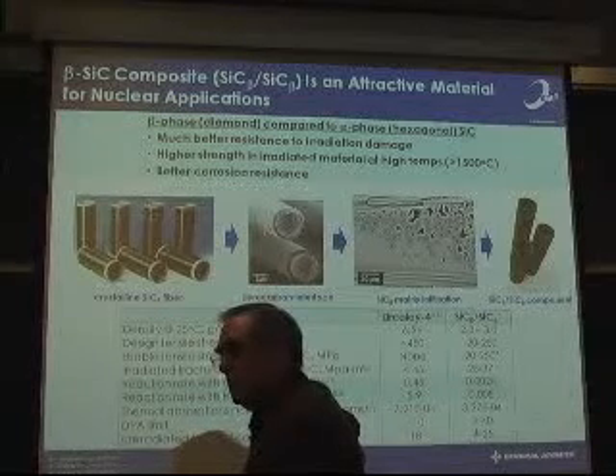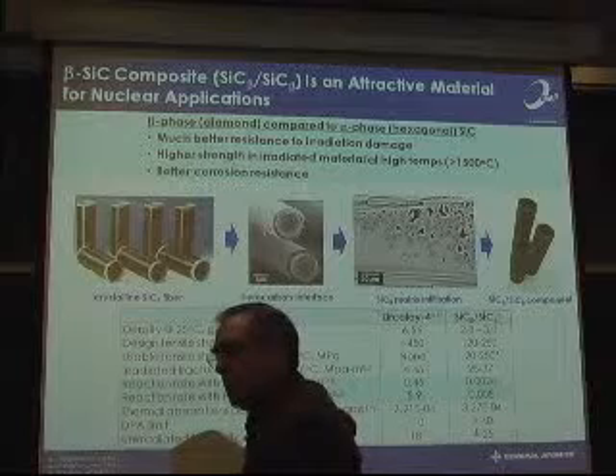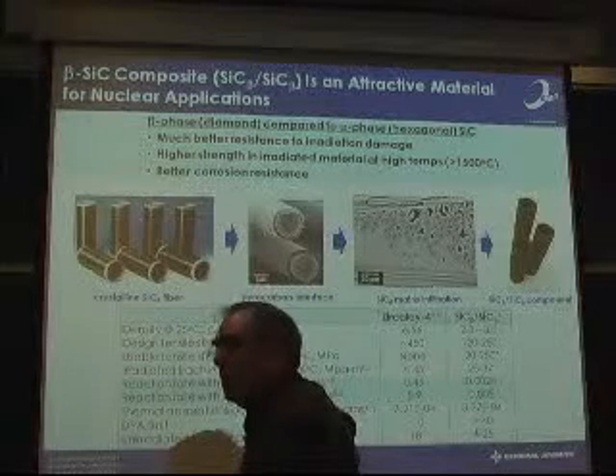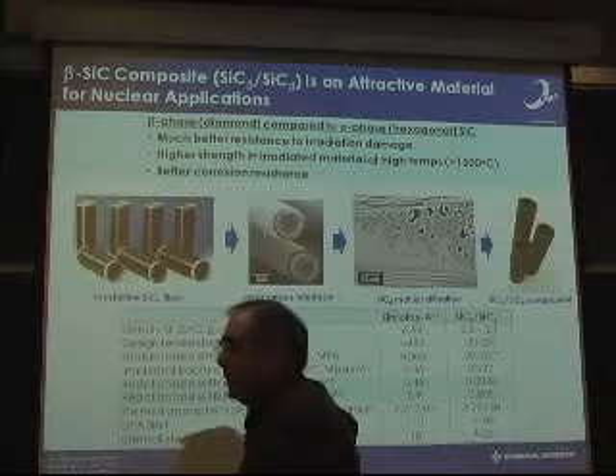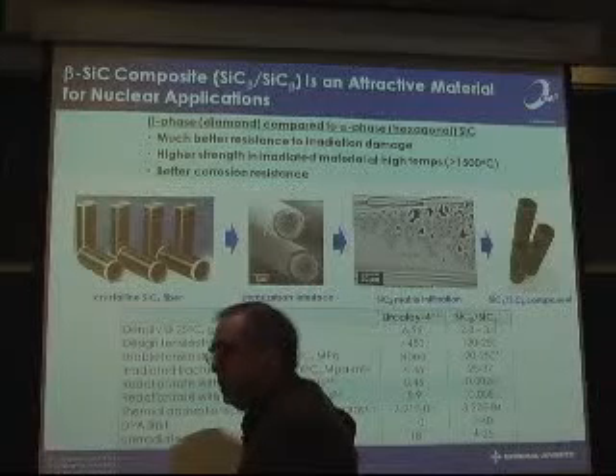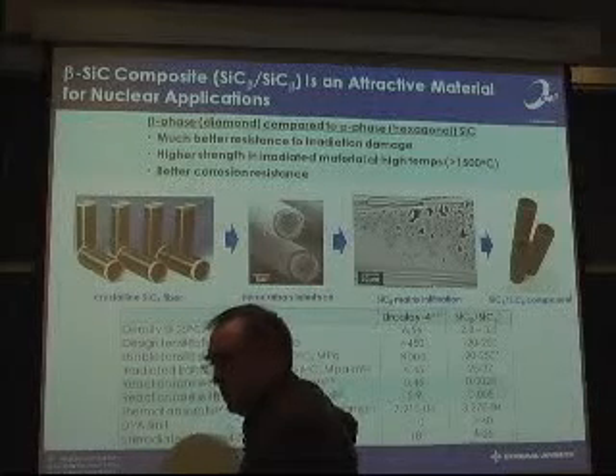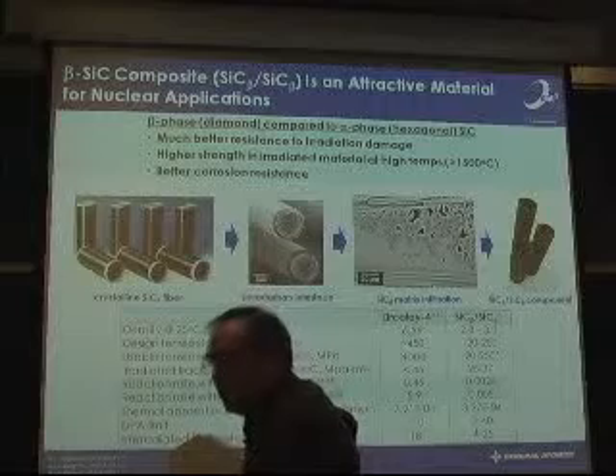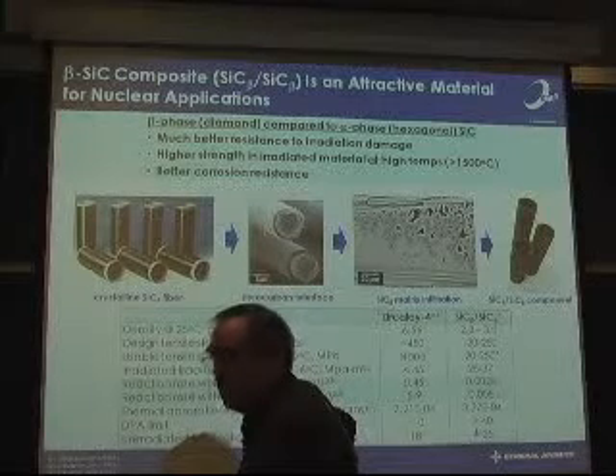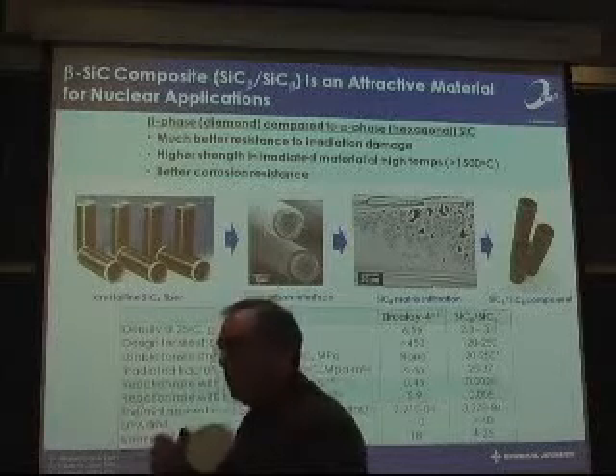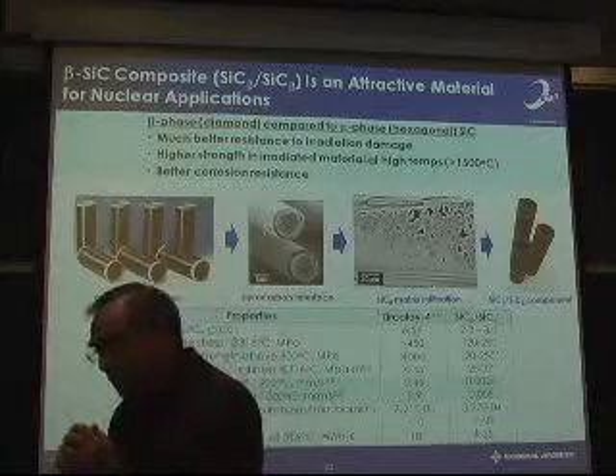For the EM2 reactor fuel, how do you accommodate the swelling of the carbide? Well, in that case, the UC has a very high creep rate, and it'll react against the silicon carbide composite clad and collapse on itself because of the porosity that we put into the fuel.